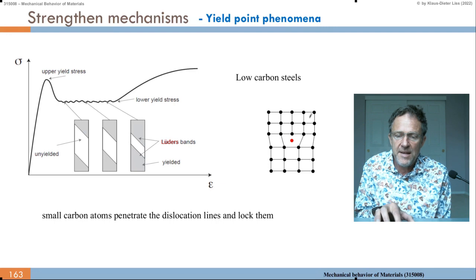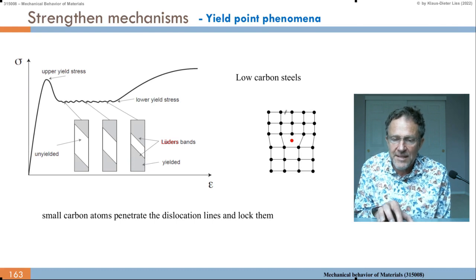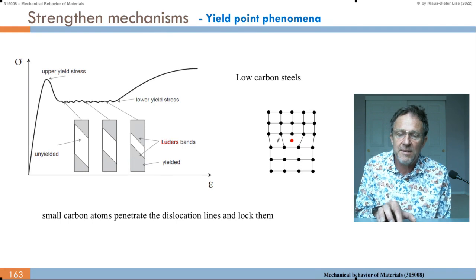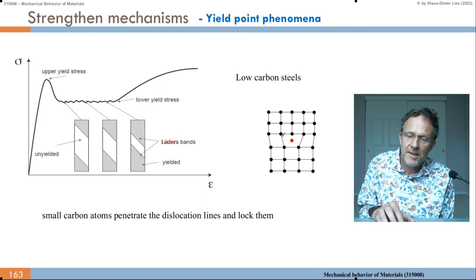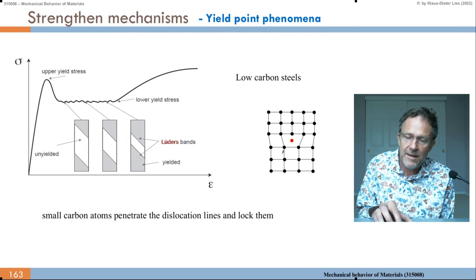Because if I put the carbon here, it takes more energy because there's less space. Here also less space. If I go far away from the dislocation, this and this is the same. But in the vicinity of the dislocation, there's more space on this side of the dislocation, less space on that side. More space than in the average crystal structure is close to the dislocation in the tensile stress field. So the carbon goes here.